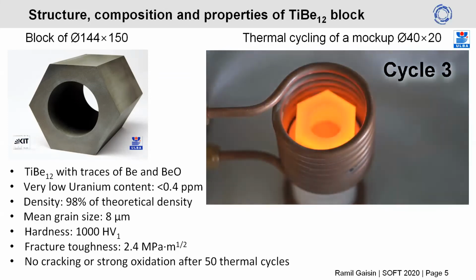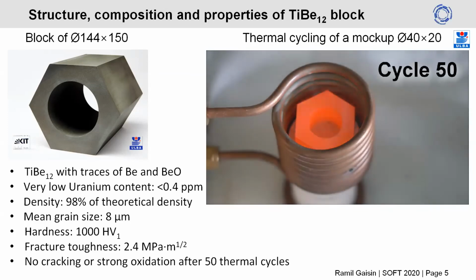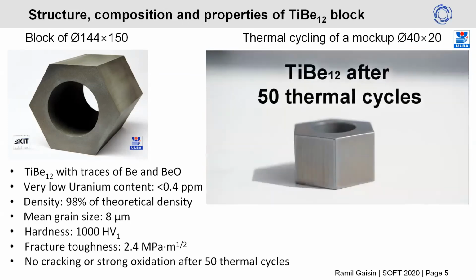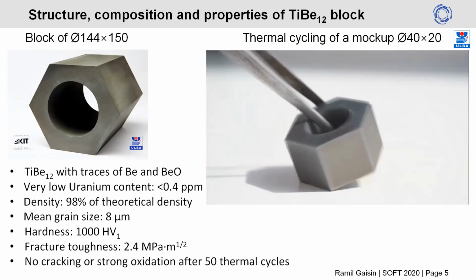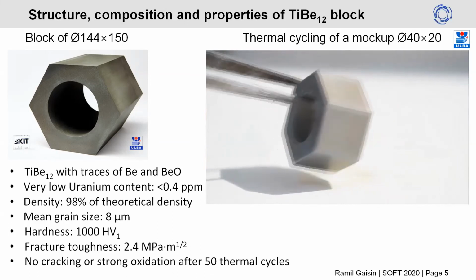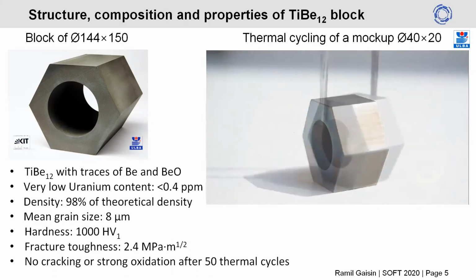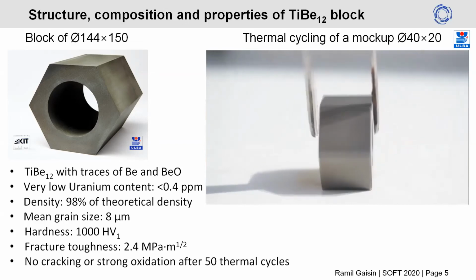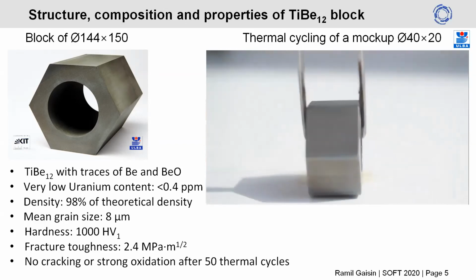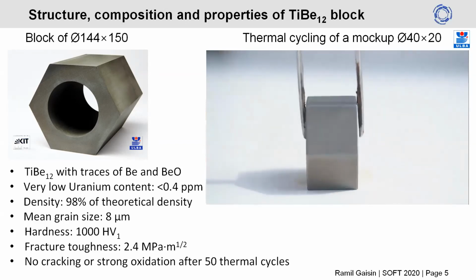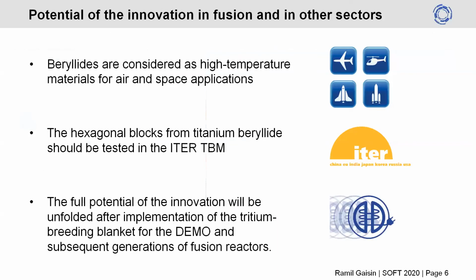More cycles with even more video acceleration and continue up to 50 cycles. As a result, there are no cracks, no strong oxidation after 50 thermal cycles. In the next step, we will test the full-size block, and the preliminary experiments were already successful. Thanks to these outstanding properties, such beryllides can be used as high-temperature materials for air and space applications.